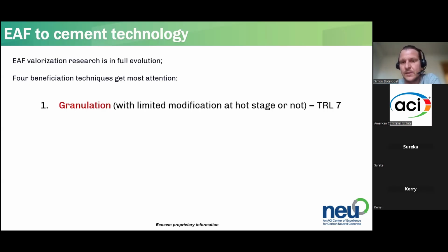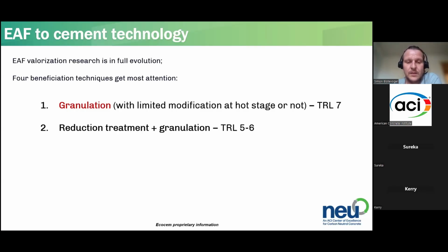And for now, there are 4 different beneficiation strategies that start to emerge. The most important one, and the one I will spend most time on today, is granulation with limited chemical modification or not, which has reached by now about a TRL of 7, I would say. Then there are strategies where people try to reduce the iron and the metals out and then granulate. So this would result in a slag that is very similar to today's blast furnace slag.